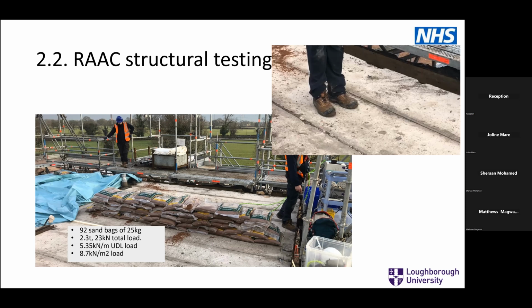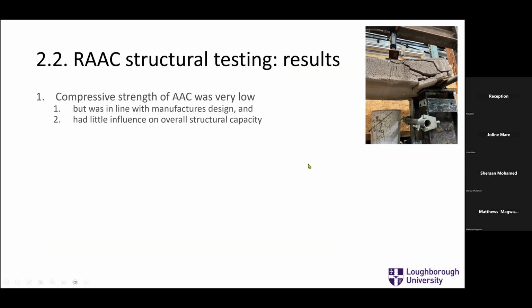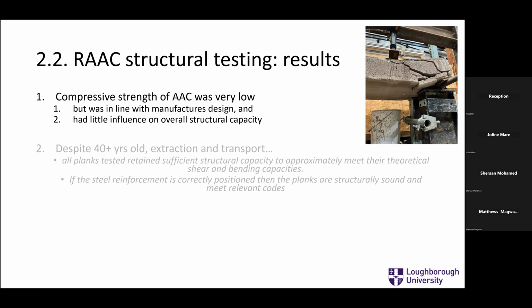So this was interesting. So well, what's going wrong? Why have some collapsed? Because the ones we're testing are actually doing very, very well. So the compressive strength I mentioned was very low, but we know that, and it was designed to be low, so that's okay. It actually has little influence on the structural capacity. If you change the compressive strength from 2 to 4 megapascal, the structural capacity, as in bending moments, doesn't change a great deal. It's the steel reinforcement that is the capacity and does the heavy loading.